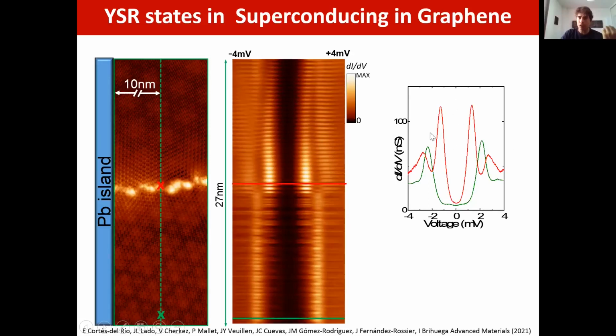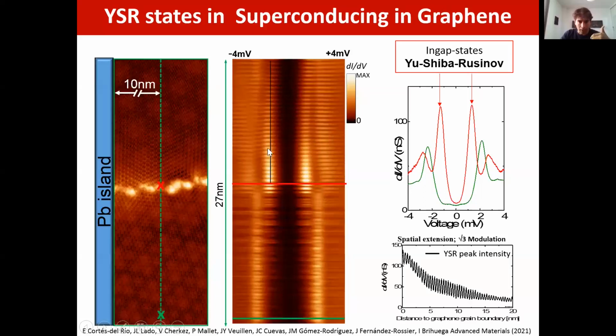And then we see immediately the appearance of these in-gap states, which are Yu-Shiba-Rusinov in-gap states. Those two peaks are these bright yellow features that we see here inside the superconducting gap. The superconducting graphene gap will be these lines that you see here, and the in-gap states that we observe are these lines. So you can see, if we make a line here around this in-gap state, that the Yu-Shiba-Rusinov states extend very far away from the defect, from the grain boundary, and also that they are modulated with the root-3 periodicity. Those Yu-Shiba-Rusinov states that we have here are peculiar in several ways. First, they originate on a region without magnetic atoms. Here, this grain boundary is just formed by carbon atoms.